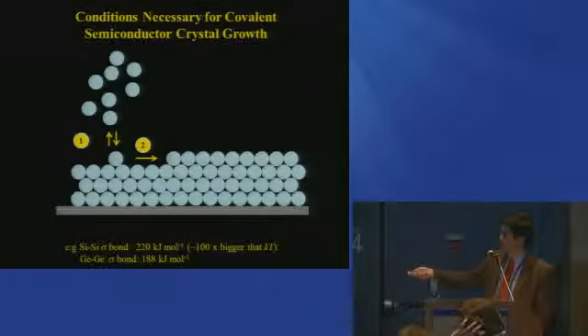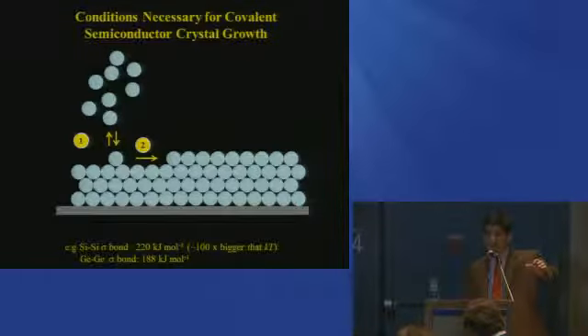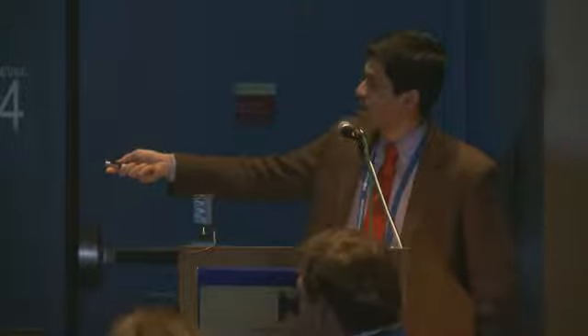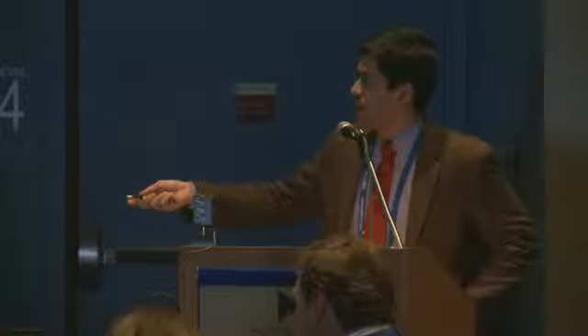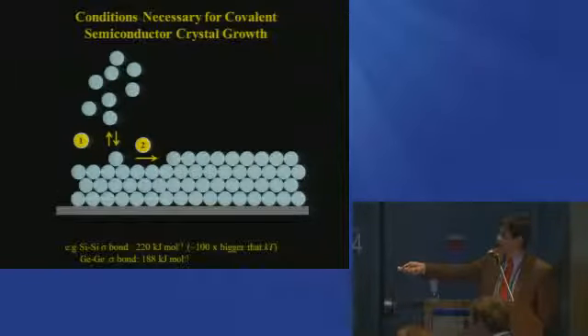The other option in terms of making a good crystal is to have fast atom diffusion. You put an initial atom down, and if it can move to find the right spot on a crystal growth front, then you can make a nice ordered layer. But on a covalent crystal like gallium arsenide or silicon, if you think about the bond energies for this atom on this crystal, these are several orders of magnitude larger than kT. So effectively, if you try to electrodeposit silicon at room temperature, you don't have this pathway either. And so what you're left with is you're always going to make, in the conventional sense, amorphous, unfortunately, not very useful material.